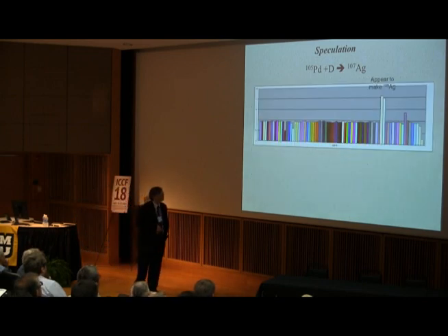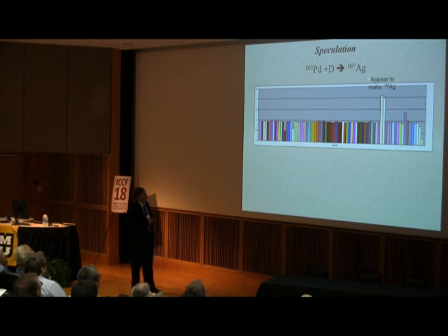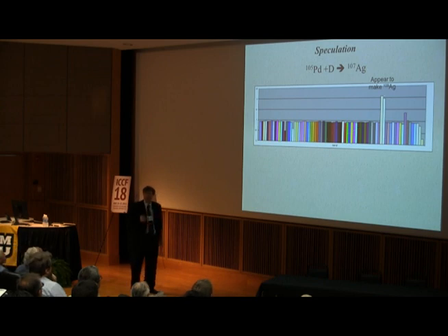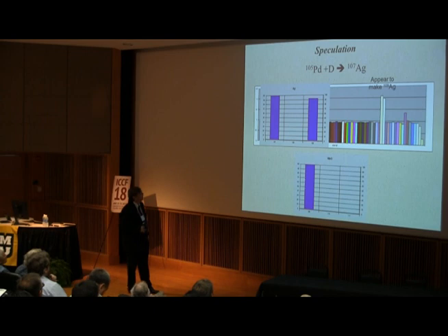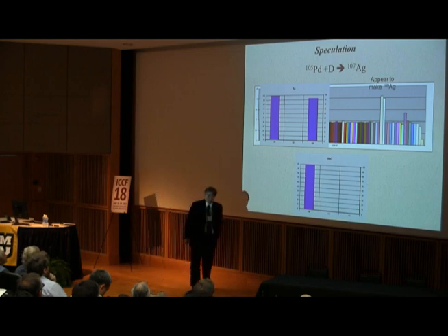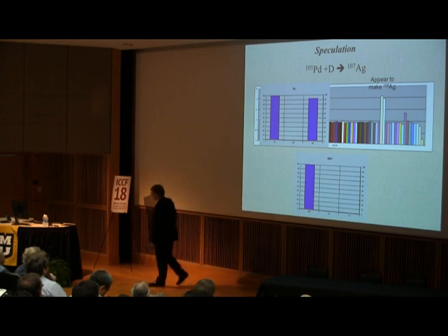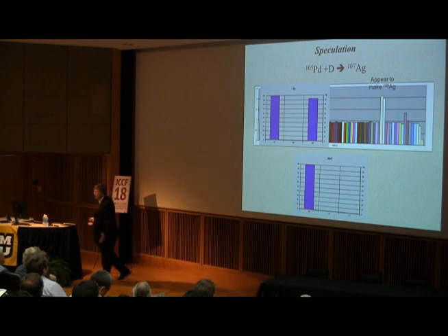Let's look at this first. Now, I appear to make silver 109. We're taking a ratio of 109 to 107. It's greater than 1. That means we're making silver 109 in these two samples. Is that the case? Well, silver looks like this, and niobium looks like this. How in the world are we getting the niobium oxide in this sample when we put it into this 10,000 degree plasma? It broke it all apart, and then it formed niobium oxide?